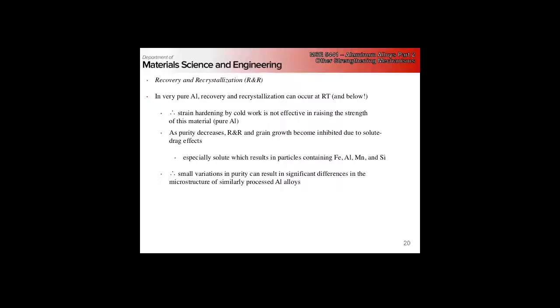Right? I'm going from a lower energy locally to a higher energy. So the way to maintain the low energy is to only move my interface at the same speed that my solute can diffuse. I'm dragging my solute along with the grain boundary. Right? That's the physical simple picture, right? If this were the phase transformation and kinetics class, right? We talk about that in quite a bit more effect,